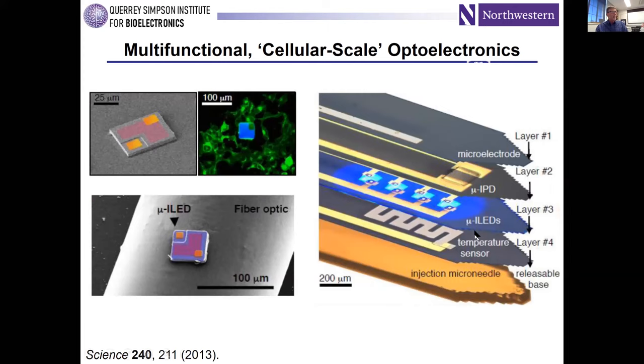We can put them on very thin sheets of plastic that we can lithographically define into filamentary needle type shapes. We can do multiple LEDs. We can wire them up using lithography. They're thin enough where you can just do edge over metallization, so wire bonding is not necessary. You just use photolithographically defined PVD metal to do this. And you end up with a device that's so thin, you have space, you have room.